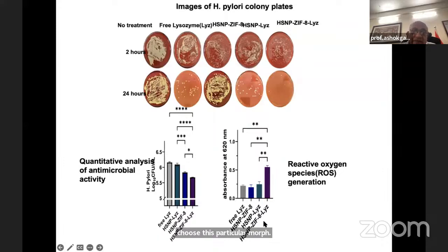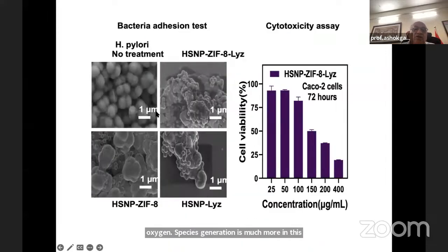And we make hollow silica nanoparticles to adhere to the H. pylori cells along with the lysozyme. And you can see that the reactive oxygen species generation is much more in this particular case. So these are microscopy images to show you that when you have the ZIF8, the particles are adhering to the cell walls, etc. And the cell viability is much less when you are using this HSNP ZIF8 lysozyme. These are on CACO2 cells, and we studied the concentration dependence of the cell viability.